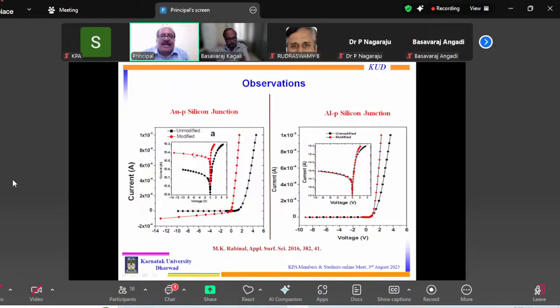I can see a low barrier height in case of gold and a higher barrier height in case of aluminum. So it means the organic molecules can passivate the surface states and open up what is expected theoretically, that the barrier height of the semiconductor metal junction should vary with respect to change in contacting metal.